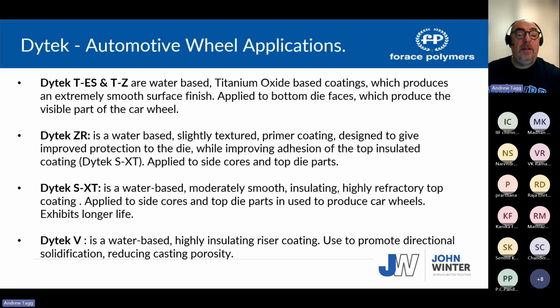Then we have Dytek ZR, which is a textured primer coating, which is sprayed predominantly not on the wheel face. It's sprayed on the side cores or the side inserts and the top die, and then we use the SXT as shown earlier on the top and side cores. The Dytek V is specifically for feeding, and is specifically for only GDC. Low pressure wheels do not require feeding, but GDC does. So in this case, this is a riser coating. So that's the four coating application that we would use for GDC. And LPDC is different.